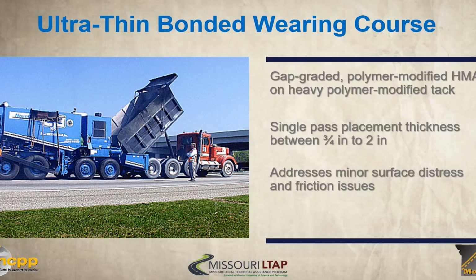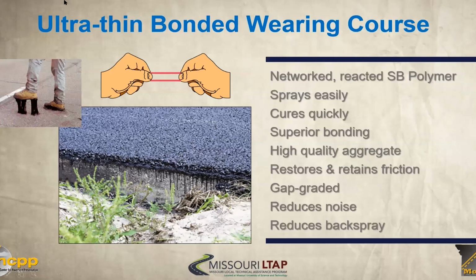In this picture it is. And so it really uses a gap graded polymer modified HMA on this polymer modified tack coat. It's a single pass treatment, and the thickness really ranges from 3/4 inch to 2 inches. And it's really intended to address some of the surface distress and friction issues, in addition to light raveling, those types of things. And this is what happens if you step in it. It's highly polymer modified, the tack coat is. You definitely don't want to stick to the road.